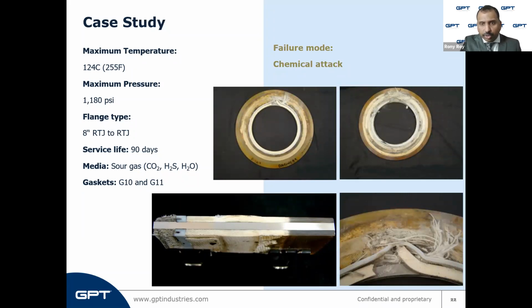The high temperature water broke down the epoxy by breaking the crosslinks, and the hydrogen sulfide, as we know from other sour gas testing, accelerated the breakdown in the epoxy by reducing the gasket's density and increasing the gasket's mass. Additionally, the hydrogen sulfide can dissolve into the water, and the carbon dioxide can as well, creating hydrosulfuric acid and carbonic acid, which can break down the glass fibers. So this domino effect led to a failure in just 3 months.